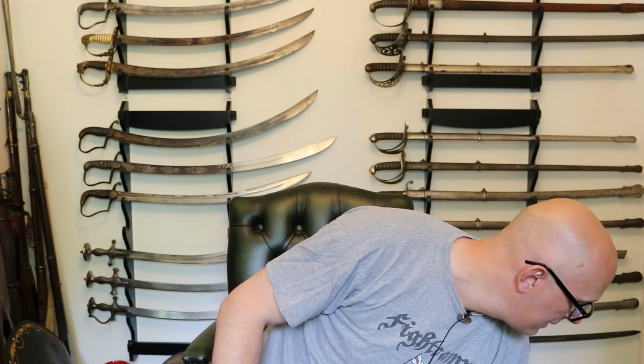Now the Japanese, they do quench the whole blade, but before quenching they cover the back part of the blade, in fact everything except for the edge and the point, with clay. That's a form of differential hardening, whereby when you put it into the water, the edge hardens much more quickly than the clay covered back of the blade, because the cold water can't get to it directly. So you end up still with a hard blade, but the edge is very much harder than the back.